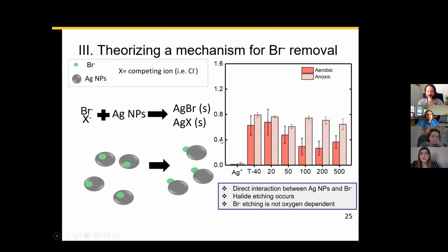the effects of bromide removal were actually coming from that complexing between the silver and the bromide. And so we saw that, if you look at the dashed graphs, the removal efficiency of the materials actually increases in anoxic experiments. We attribute that to the direct interaction between the silver nanoparticle surface and the bromide, which we attributed to the halide etching that is actually observed when we synthesize silver nanoparticles. We use halides, namely chloride, iodide, and bromide, to tune the shape of our silver nanoparticles, but this is the first time that we have actually observed this application for the halides in water treatment.